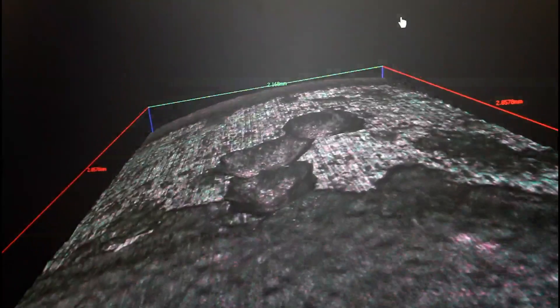We use these metrics to predict exactly where the specimen will fail. The specimens are then fatigue-tested. We then use a high-resolution scanning electron microscope to observe the fracture surface and determine the points of failure in a process known as fractography. The data collected during fractography can be used to determine which type of pit initiated crack growth and which type led to failure. So far, we are 85% successful in predicting which pit caused failure, and we are improving with every new data set.